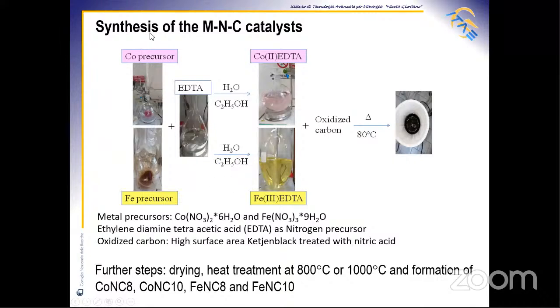Here we can see an in-house metal nitrogen carbon catalyst. The cobalt EDTA and iron EDTA complexes were prepared by mixing the EDTA solution with the cobalt 2+ or iron 3+ precursors. The color became pink for cobalt EDTA and soft yellow for iron EDTA when a stoichiometric amount was added to the solution. Finally, an oxidized carbon, that is carbon black treated in nitric acid, was mixed to the sol gels. The solvents were evaporated and the impregnated product was dried.